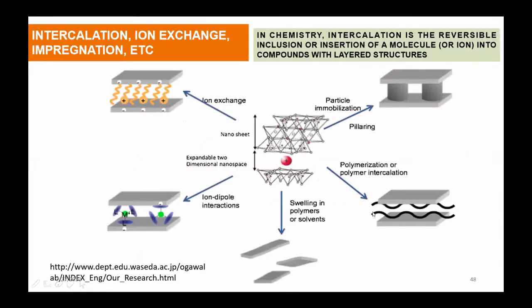Intercalation, impregnation, and ion exchange are for catalysts. We insert materials into layered materials. The definition in chemistry of intercalation is the reversible inclusion or insertion of molecules or ions into compounds with a layered structure. But nowadays, the term reversible is no longer used, because it is not always reversible. For example, in the formation of pillared clay, the process is not reversible, because the pillar cannot be removed from the layer without destroying the structure. So this layered material we can mix. We can insert active material through ion exchange, or particle immobilization in the pillared clay, or polymerization, etc.